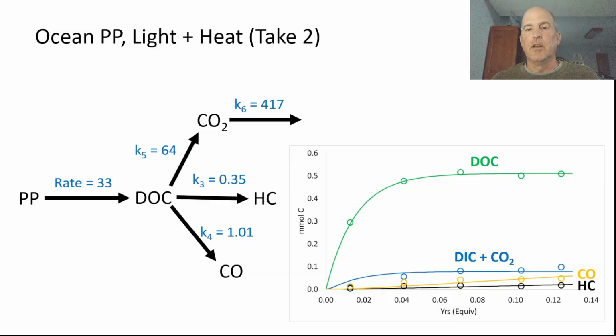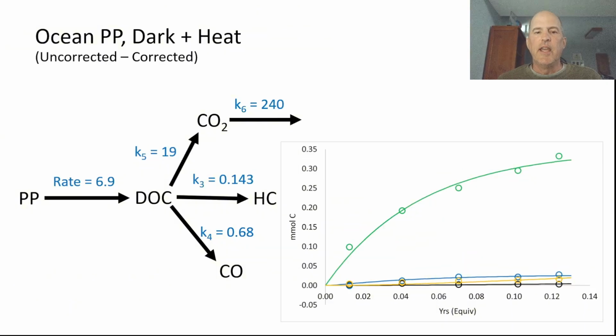Okay, so that should compare to, in theory, the linear fits that are already in the paper. Now this was for light plus heat. So we haven't corrected for the degradation, the thermal degradation due to just heat yet. And the way you have to do that is I had to take their uncorrected plot minus their corrected plot to back out what the degradation pattern must have looked like for their control experiments. And so that's what I've done here.